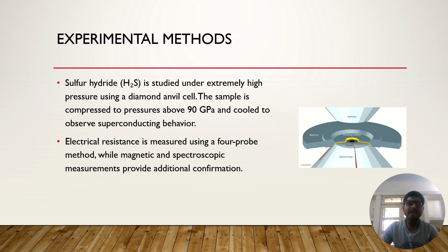And as the temperature is lowered, the resistance is continuously monitored. A sudden drop to zero indicates the onset of superconductivity. In addition to electrical measurements, magnetic field dependence is also studied. Applying an external magnetic field suppresses superconductivity, which helps confirm the presence of Cooper pairing.